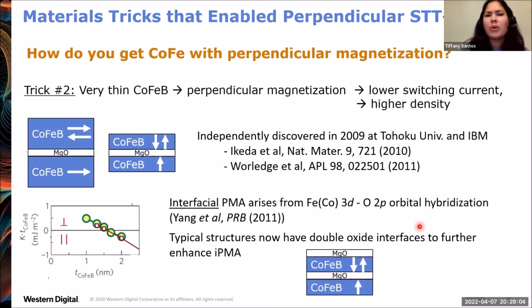Okay. The other trick is, how do you get cobalt iron with perpendicular magnetization? Because cobalt iron in the bulk form really wants to be in plane, and it is used with in-plane orientation for reed heads. But for spin transfer torque MRAM, we want perpendicular magnetization because that will lead toward a low switching current and a high density memory. And the way that you get perpendicular magnetization is by thinning down the thickness of the cobalt iron layers here. So this trick was found independently by these two groups here in 2009. And it's understood that an interfacial perpendicular magnetic anisotropy arises from orbital hybridization between the iron and the oxygen. And this gives rise to an interfacial perpendicular magnetic anisotropy that dominates over the bulk in-plane one.